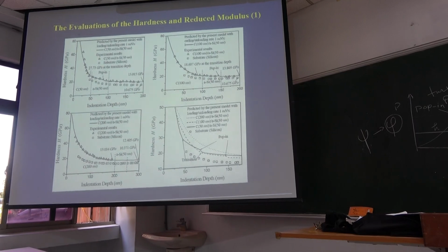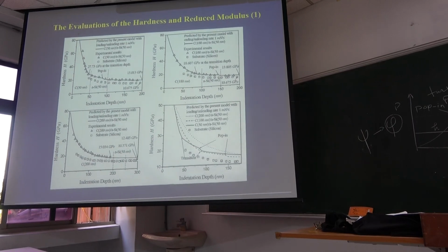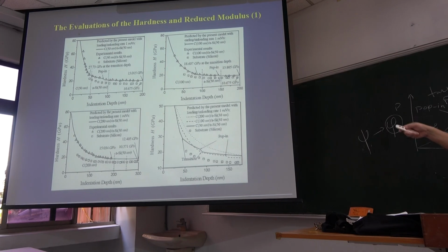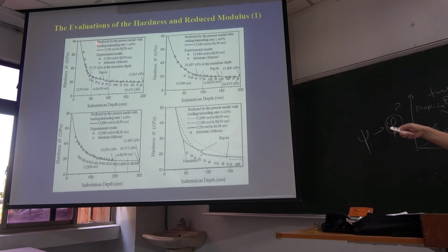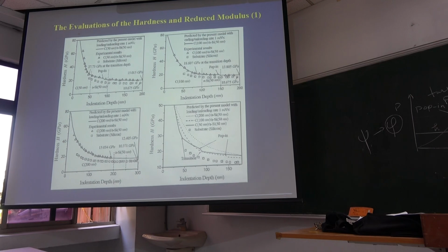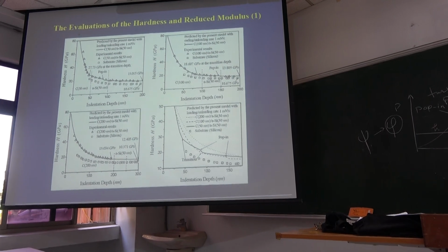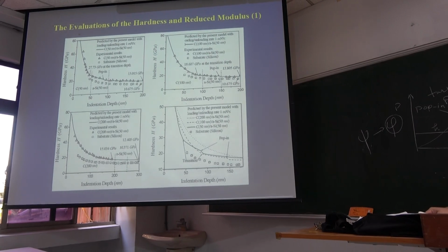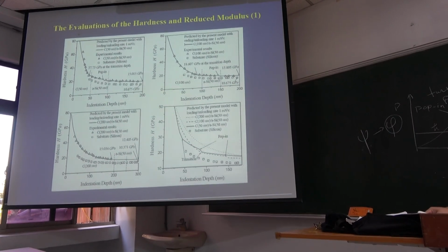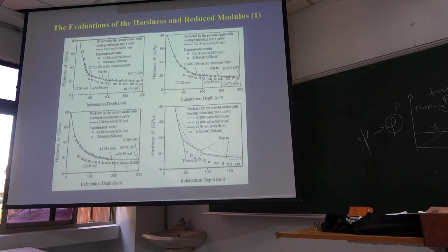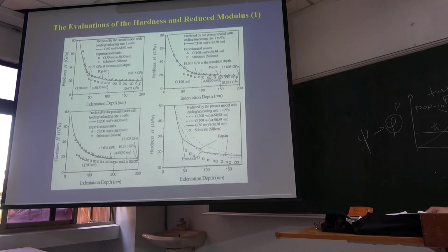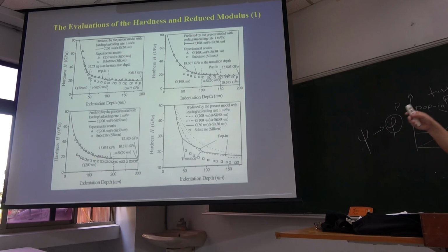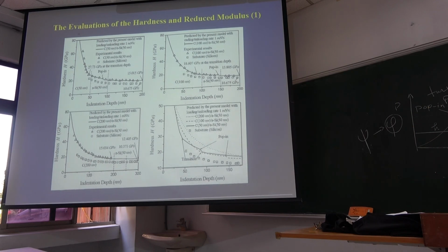In the future, when you have a coating film and use nano indentation to show your property, you have to show me the maximum load you set. Second, the indentation depth you give. The maximum indentation depth you have to show me, and then your loading rate I will have to see. So all these parameters are important.